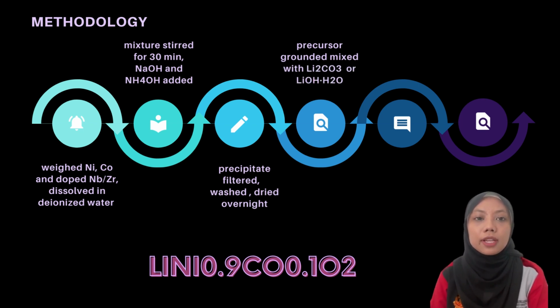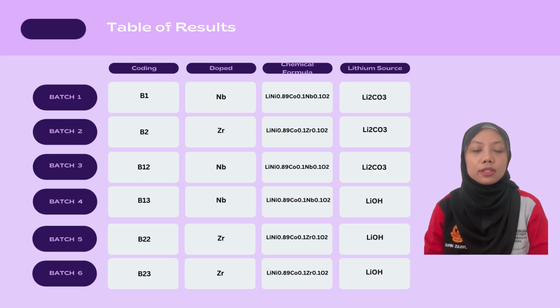The precursor was extensively ground after being combined with lithium carbonate or lithium hydroxide. The mixture was sintered at elevated temperature. The materials were characterized using XRD after they had undergone the annealing process. The table shows the synthesis material with the chemical formula for each batch. I can conclude that batch 1, batch 2, and batch 3 do not reach purity, while batch 4, batch 5, and batch 6 are pure.